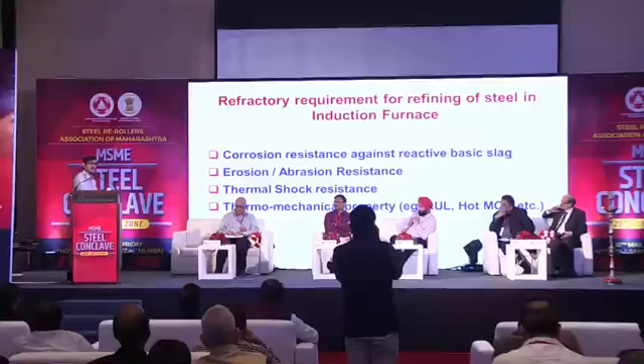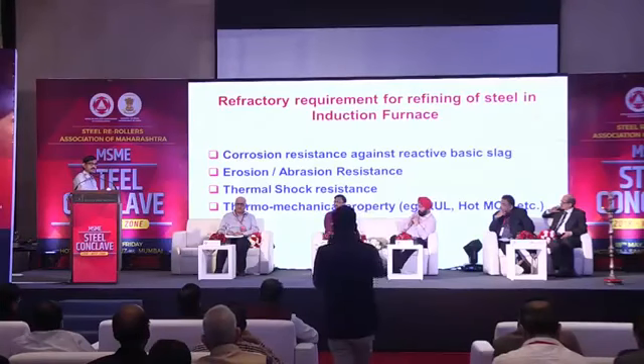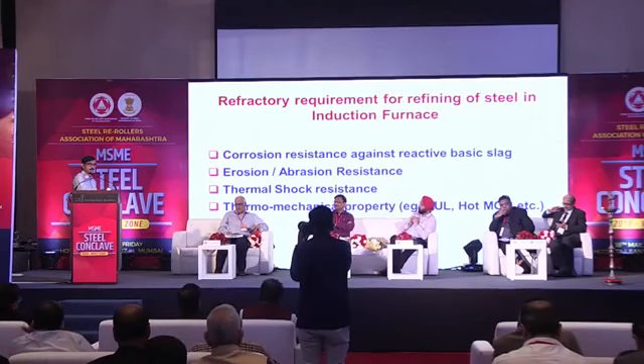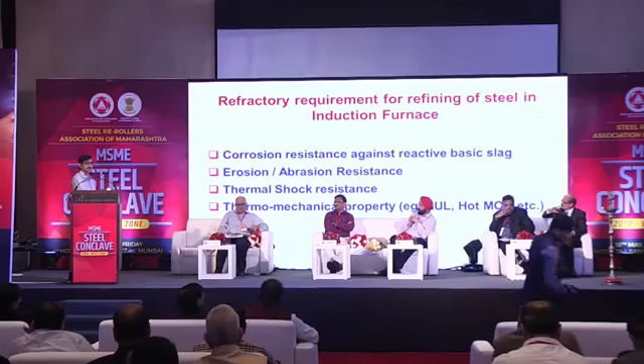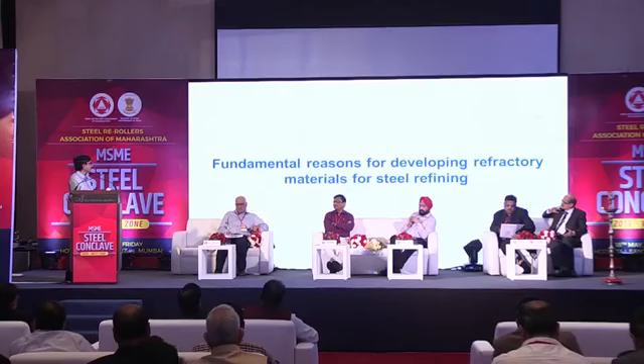So we developed a basic ramming mass, the magnesite-based ramming mass, and the most important properties are corrosion resistance against the basic slag, erosion and abrasion resistance, and thermal shock resistance. We initially started work with the magnesite-based ramming mass. The problem is that pure magnesite refractory has very low thermal shock resistance, that is, spalling resistance. The main target is to develop a basic ramming mass and improve its thermal shock resistance, then automatically you will achieve the goal.